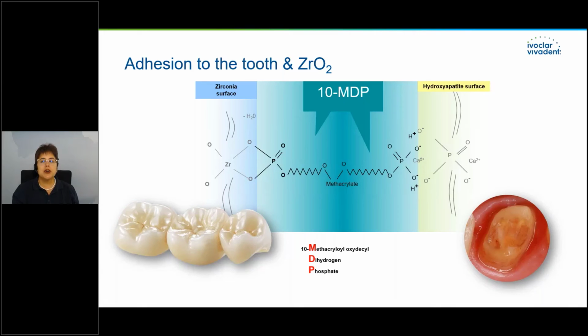And if we're working with lithium disilicate, with glass ceramic, then we need a separate pre-treatment for this glass ceramic, like hydrofluoric acid and Monobond Plus, or the newest Monobond Etch and Prime. We already spoke about it. And on the other hand, the MDP is also reacting chemically with the hydroxyapatite surface. Sorry for that.